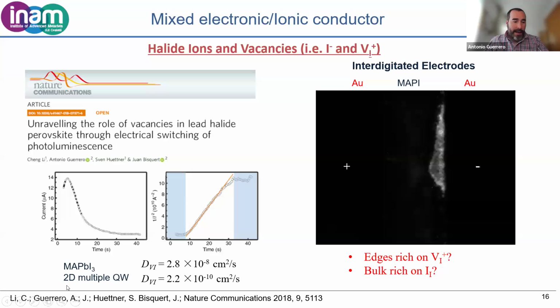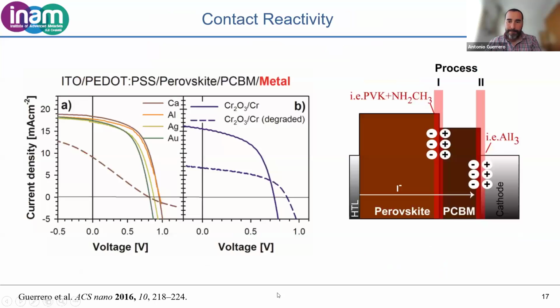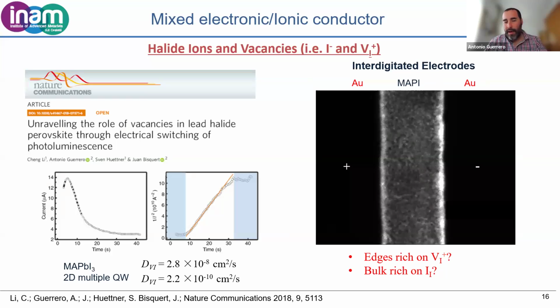iodide. And if we, for example, use large cations that disrupt the chemical lattice, generating 2D domains, layer domains, in that case, the ionic diffusion is a lot lower, two orders of magnitude lower. This is one example of how we characterize the intrinsic properties of ion migration of the solar cells. But we have other techniques as well.